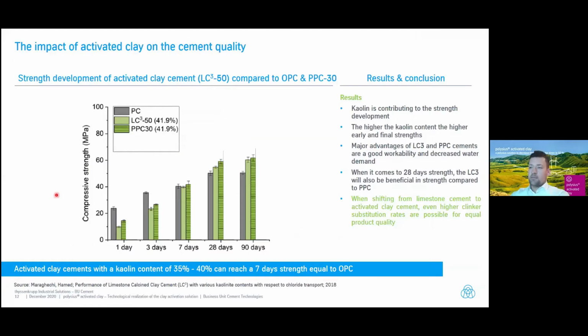Okay, just to give you some indications on the quality of such a cement, please have a look, first of all, on the left-hand side. So what you see here is the compressive strength over the days, right? So this is the first day strength, 3-day strength, etc. We are comparing a standard OPC, which is the left gray bar in all cases. And this we are comparing to a so-called LC3-50 composition with around 40% kaolin in the raw clay. This is in brackets. This is meaning the kaolin content of the raw clay.